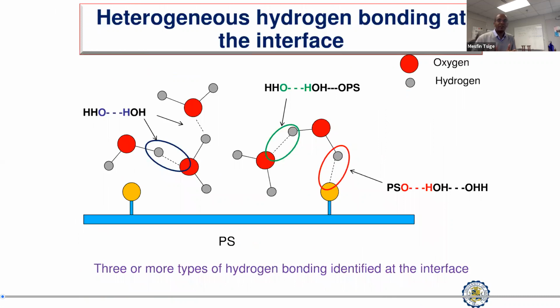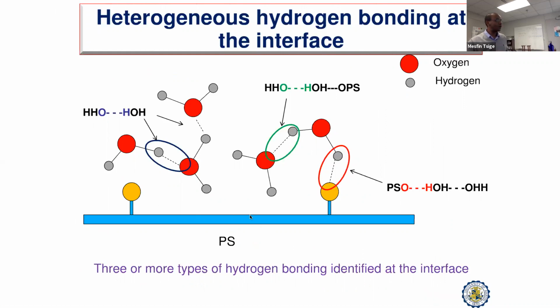So what we have observed in our case is there is a heterogeneous behavior in the hydrogen bonding at the interface. Heterogeneous in a sense is that this is a cartoon showing, let's say, this is our polystyrene surface. These are the oxygen part. And then we have water molecules. These are what we call interfacial water molecules. So a given interfacial water molecule may either form a hydrogen bond with the substrate, or it may be forming a hydrogen bond with another water molecule which forms a hydrogen bond with the substrate, or neither of the two. It will be interfacial, but not involved in any form of hydrogen bonding with the substrate. These three show a completely different behavior.